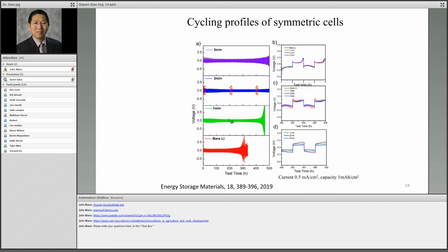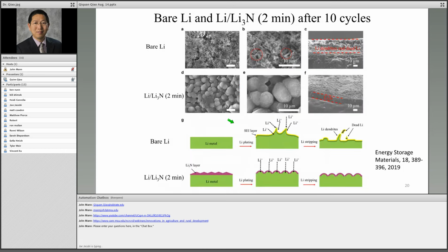And then at 3 minutes you see some decay in the capacity of the batteries. So that shows that 2 minutes is the best. If you just use 2 minutes of lithium nitride growth in nitrogen plasma, you can significantly improve the capacity, and also the cycles of this lithium metal battery.